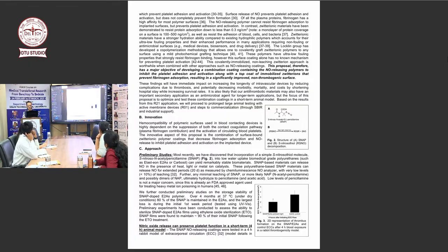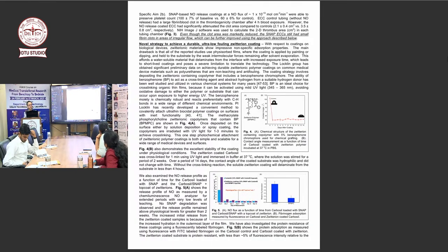So here we showed preliminary work, we have done nitric oxide work, but the issue is some thrombosis still happens without zwitterion in that figure. Then we say we have covalently bound zwitterion to surfaces and look how the contact angle changes with zwitterion. It's stable for 14 days.